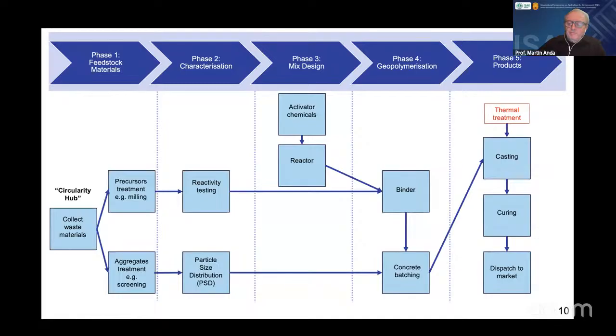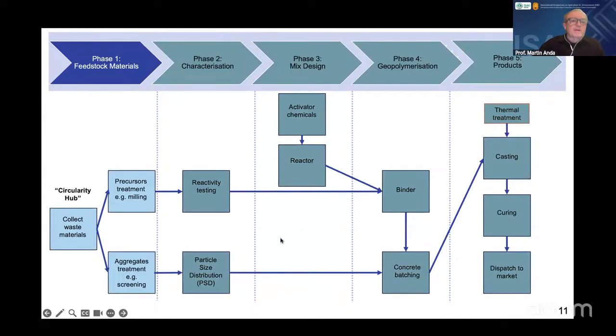If we start with phase 1, you can see there that we want to collect the waste materials. It could be from these tailings storage facilities. It could be from the rice husk ash and the boiler ash around Sri Lanka, or the fly ash dams. And what I've been looking at is these collection areas. We could call them circularity hubs, and we may bring together a range of different materials that we can use as both the precursors to make the geopolymer concrete, or to be used as aggregates in the concrete itself. And so we may need some pre-treatment here, milling of the fly ash, for example, or screening of the aggregates if, for example, it's construction and demolition waste or coarse mine tailings.